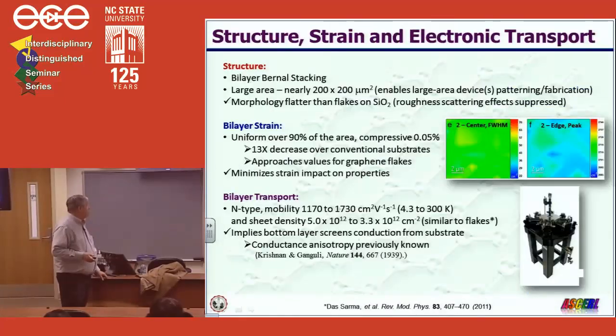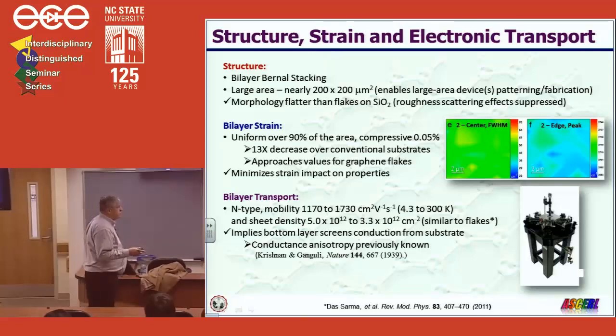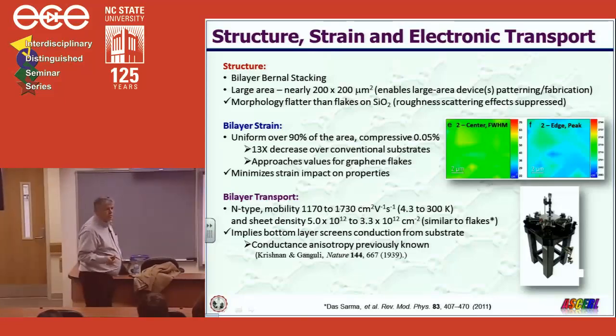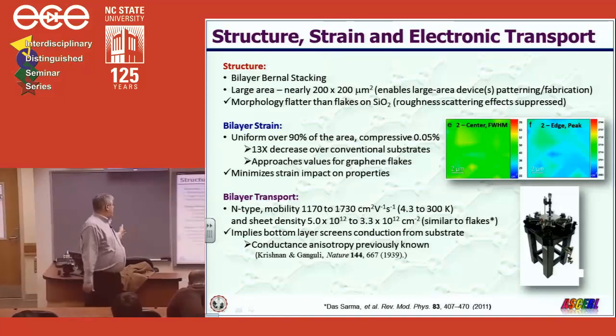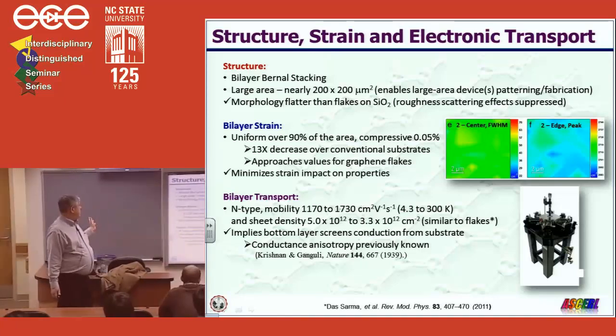So we took this one step further. We did some preliminary measurements on the transport properties, from 4K to 300 Kelvin. And we got mobilities that were roughly 1100 to 1700 and sheet densities on the order of 5 to 3 times 10 to the 12.